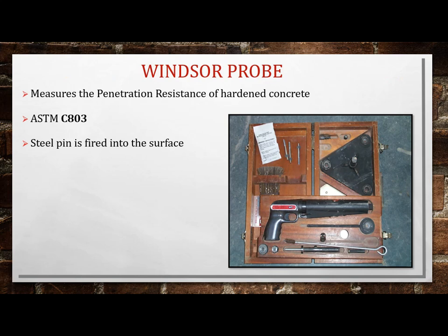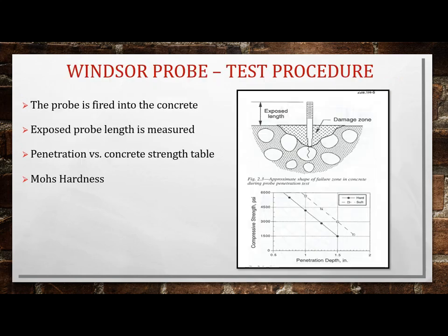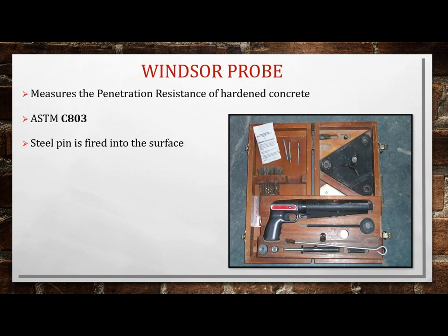Another test is a Windsor probe. It's kind of an old school test where you open it up, you put in a 20 caliber shot, you put a steel pin, you actually fire a steel pin into the surface of concrete. And there's tools so it lines you up. And so as the probe is fired into the concrete, the exposed length is measured. And it's a regression, penetration versus concrete strength, because soft concrete is going to penetrate deeper. Hard concrete, the penetration won't be as much.